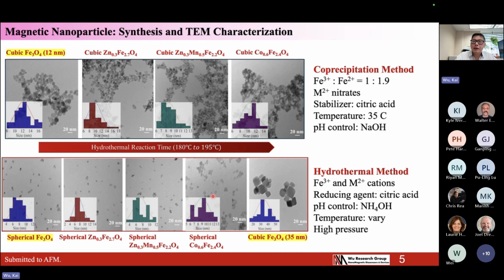So my lab can produce nanoparticles by different methods, like the co-precipitation method and the hydrothermal method, which I present in today's talk. In the co-precipitation method, we use ions as the precursors, and we can dope divalent ion nitrates into it. For example, with iron oxide Fe3O4 nanoparticles, we can dope divalent elements such as zinc, manganese, and cobalt to change the anisotropy and MS values of these particles to vary their relaxation dynamics for biomedical applications.